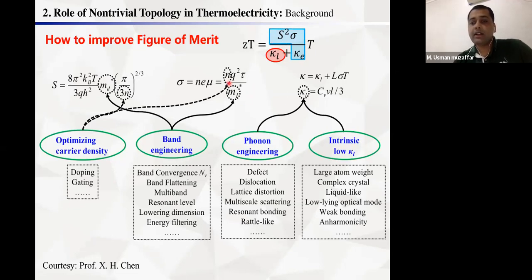You can see the electrical conductivity is directly proportional to the carrier concentration, and this carrier concentration is also inversely proportional to the Seebeck coefficient, as I mentioned previously. So if we want to optimize the carrier concentration, we usually do doping, gating, etc. Moreover, the effective mass is inversely proportional to the conductivity, and directly proportional to the Seebeck coefficient. So we also need to optimize this parameter. We usually do band engineering, which includes band convergence, band flattening, multiple bands, and resonant levels, etc.